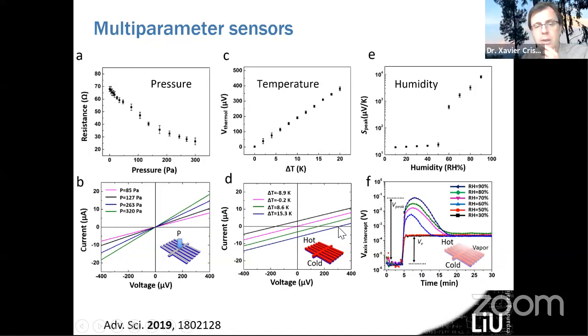Very nice. Now let's have a look at the humidity. I told you that at some humidity level, ions kick in, and they will be seen as a peak in the voltage versus time. Here, indeed, for these materials, we succeeded in making this aerogel with this feature, where you see that the peak is depending on the humidity. The Seebeck voltage at the peak is depending on the humidity.